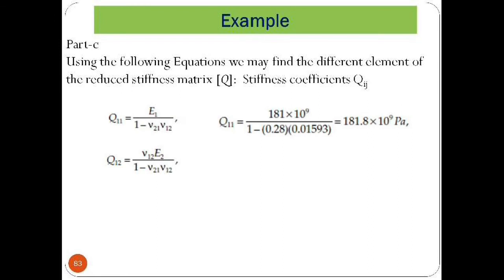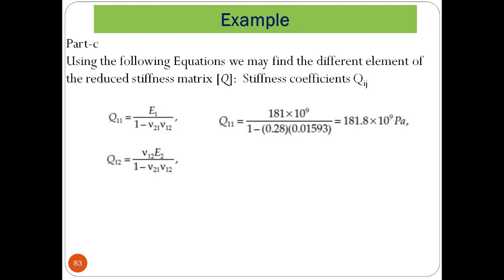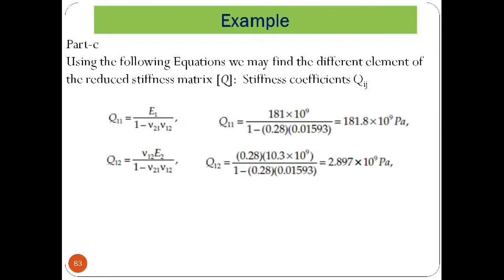Now similarly, Q12 equals nu12 E2 divided by 1 minus nu21 and nu12. And Q12 will be calculated as 2.897 into 10 to the power 9 Pascal.